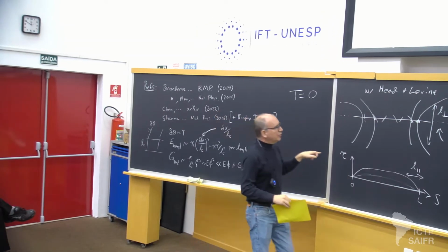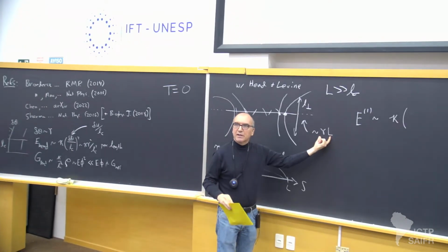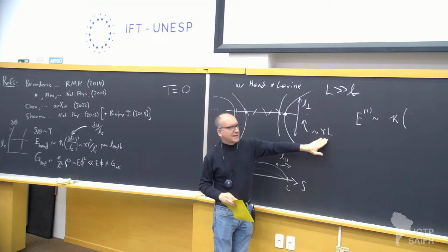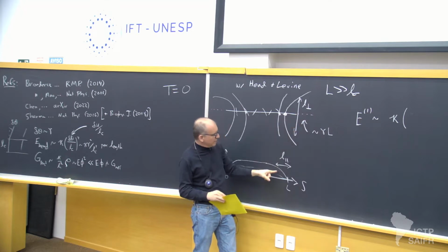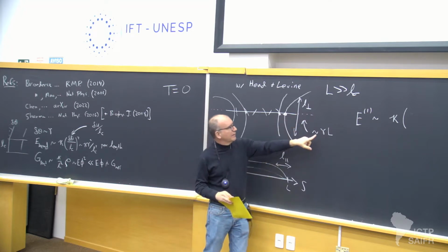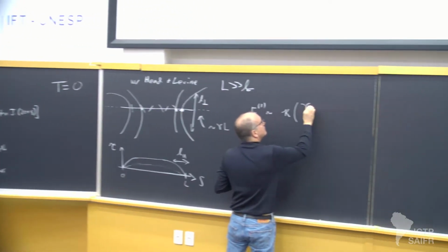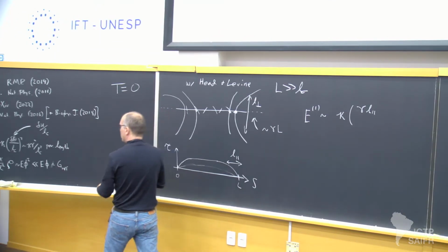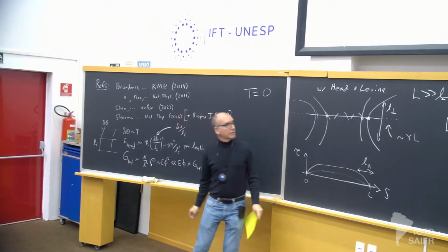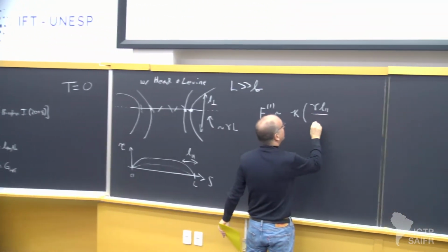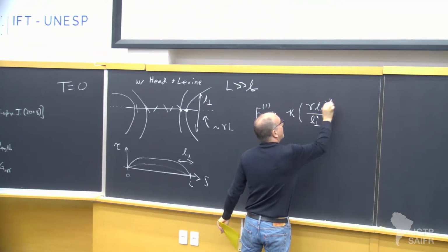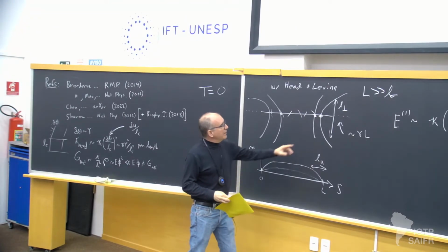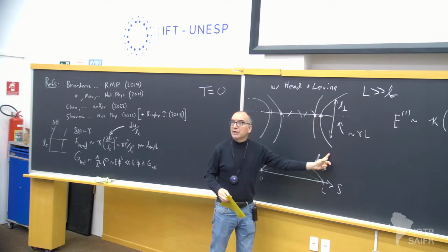But the degree of that longitudinal displacement is actually this. It's big. Actually, no, this would be if the full fiber could relax. This contraction with this argument is going to be taking this length times the strain. And then I divide by 2 powers of the scale over which the bend occurs. That's going to be my L perp. And then I square the result. That's the bending energy associated with one of these fibers that's meeting transverse.